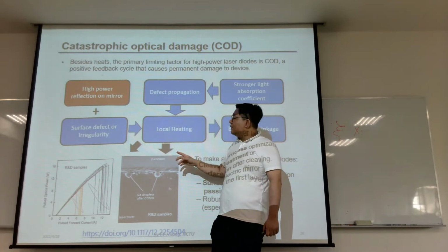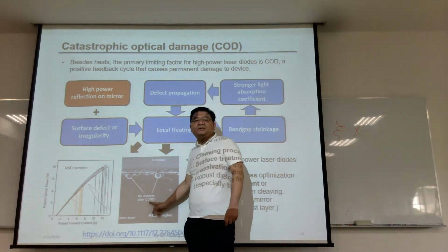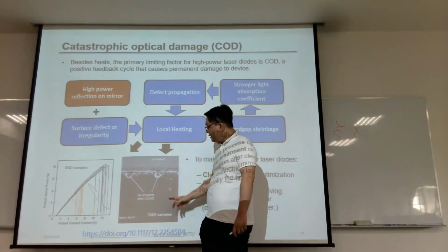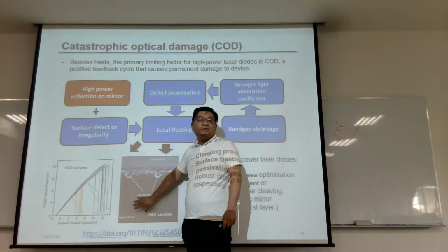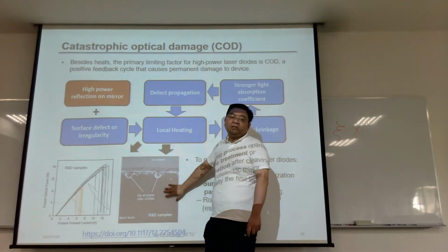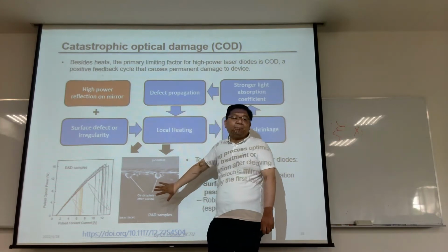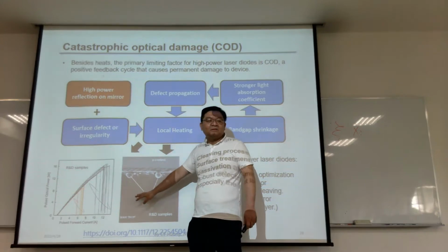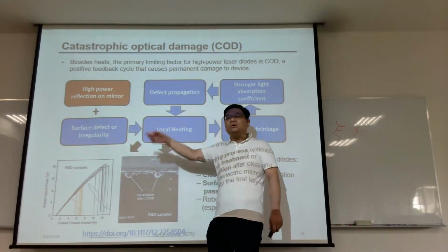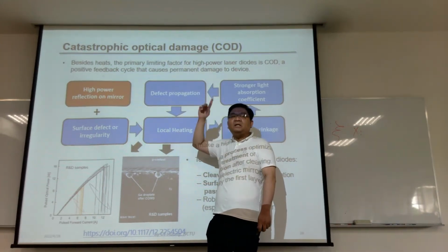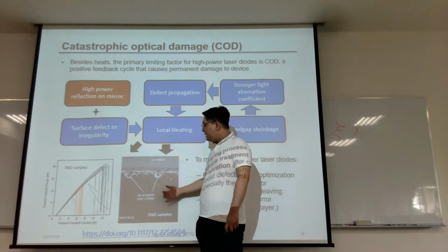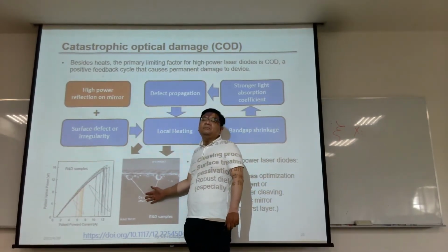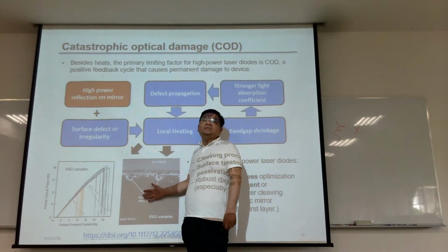After the facet is burnt, because of this kind of recycling energy, you will get a lot of defects at that point. So your reflectivity reduces, and your mirror loss increases a lot. At the beginning, you might have R equal to 99% by multi-layer deposition.